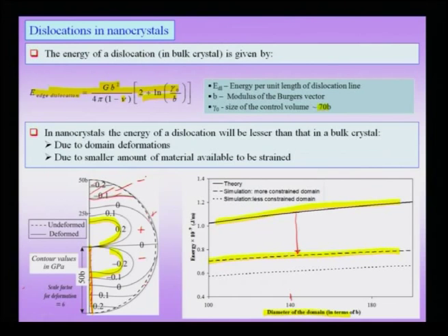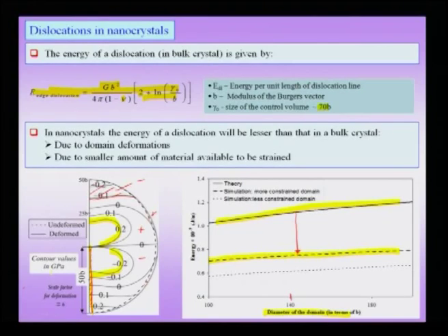Though the top-down symmetry is approximately maintained as in the case for an infinite crystal, you see that the sign switches as you go towards the top free surface, and therefore the behavior is different from that of a bulk crystal or an infinite crystal, where the entire half space is purely of one sign of stress. So to summarize this slide,